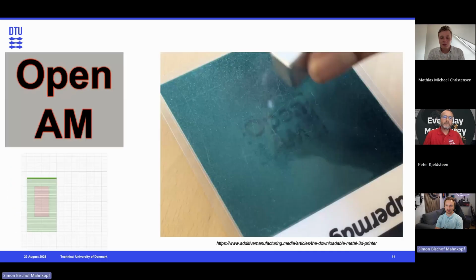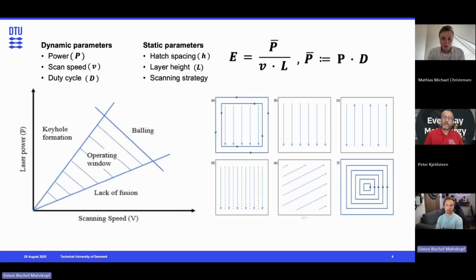Well, if we start with the parameters, we can go back to what we talked about before, where normally you use the power or the scan speed to adjust how much energy you're putting into an object. We went one step further and also looked at the duty cycle, which is, when you have a pulse laser, the percentage of on time. And by doing that, you can also modulate the laser power by turning it on and off. And we use these three parameters as they are dynamic parameters that are not geometry based. So when you change the hatch spacing or the layer height, if you do that dynamically, it will have geometrical effects, and therefore we chose to look at those three specific parameters.